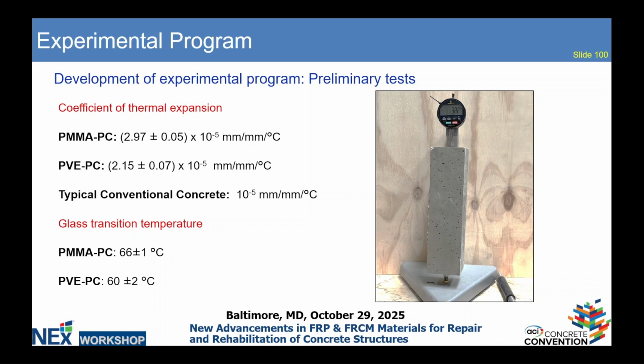As Mr. Stenko told us earlier, in the PMMA polymer concrete, we didn't have a separate hardener. The hardener was already mixed with the fine aggregate, or the sand. So the product that we used for testing the glass transition temperature wasn't a pure polymer resin, but a scrap from the concrete, which may have included sand and other impurities with it. So we are not comfortable that this is the glass transition temperature of the resin itself, but this is the glass transition temperature that we obtained from a scrap that we got from the polymer concrete.